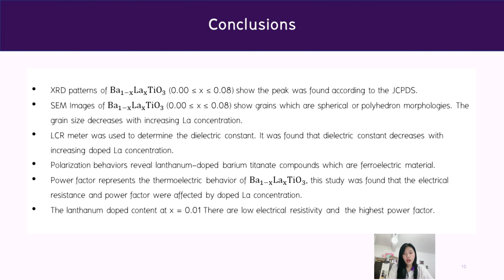This research found that the XRD pattern of barium titanate doped with lanthanum shows peaks according to the JCPDS, and the SEM image of barium titanate doped with lanthanum shows grains with a spherical or polyhedral morphology. The grain size decreases with increasing lanthanum concentration. The LCR meter was used to determine the dielectric constant. It was found that the dielectric constant decreased with increasing doped lanthanum concentration.